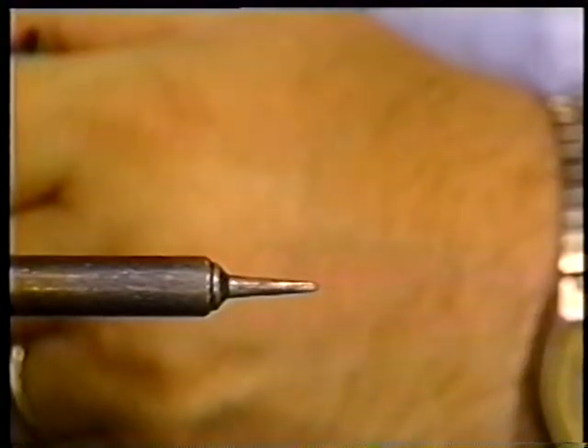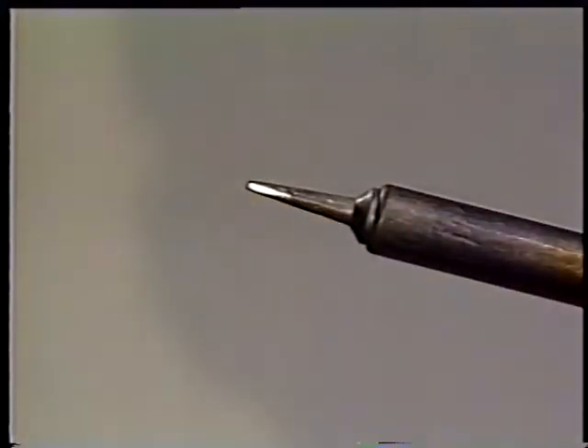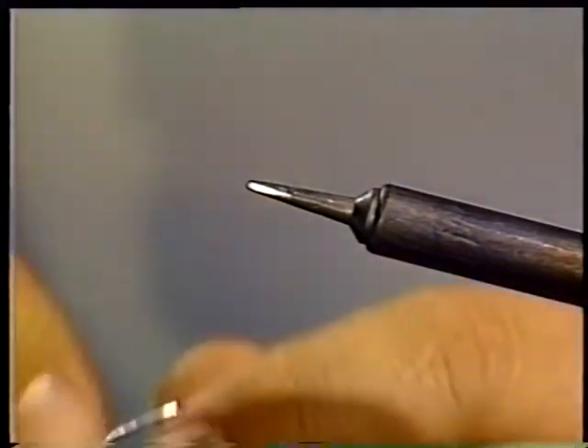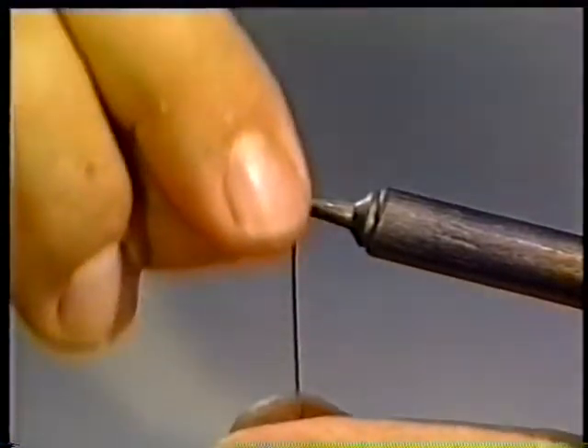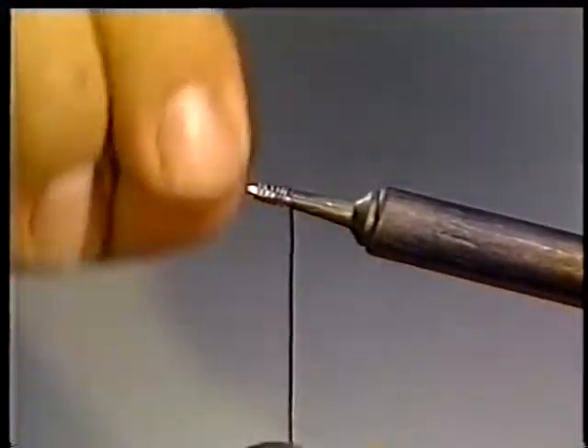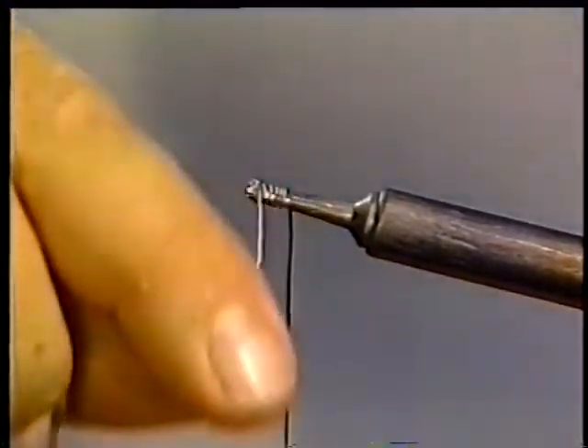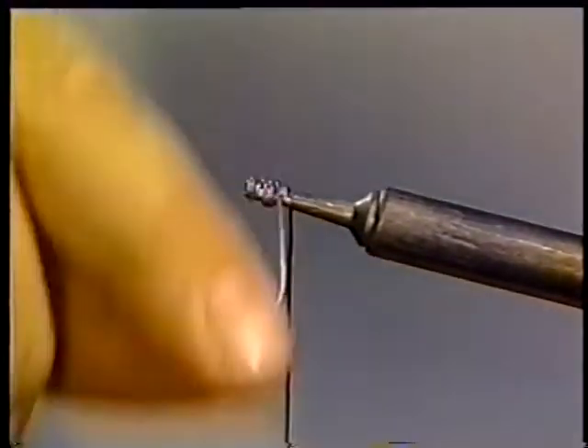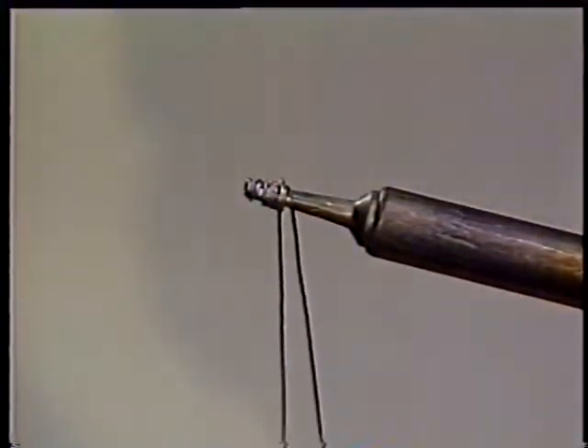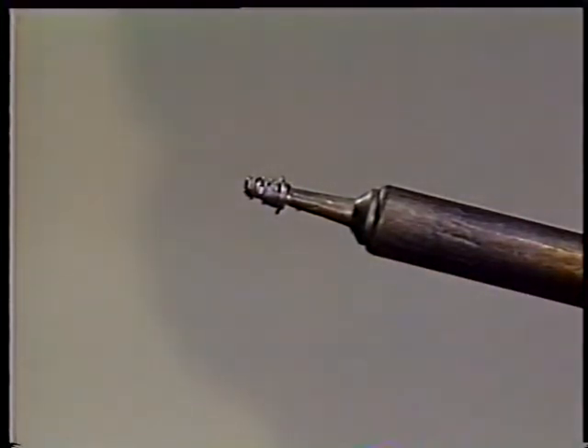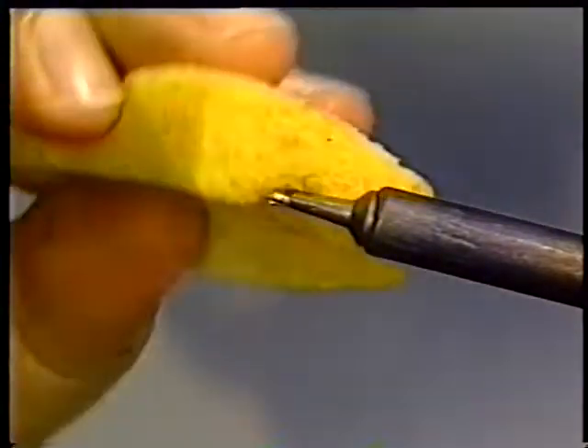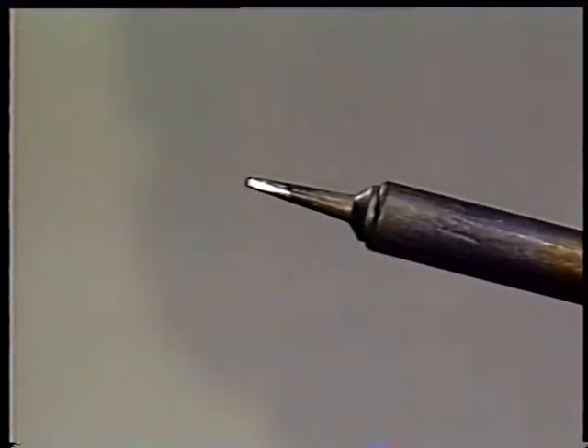The next step is important, whether the tip is new or newly cleaned, and that step is tinning. Applying a protective layer of solder to the exposed metal of the tip. With the iron at room temperature, wrap rosin core solder around the tip and clip the ends. Plug in the iron. Wait for the solder to melt. Wipe off the excess solder and the iron is ready for immediate use.